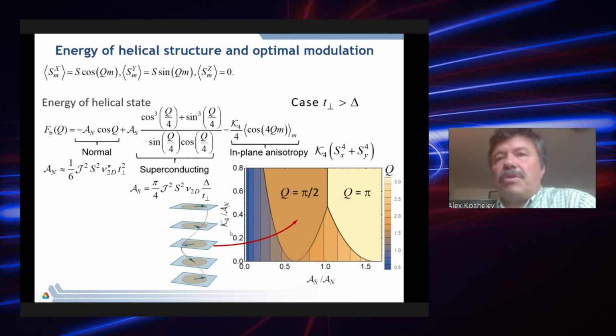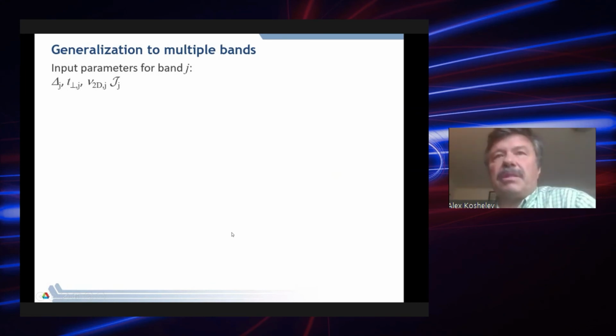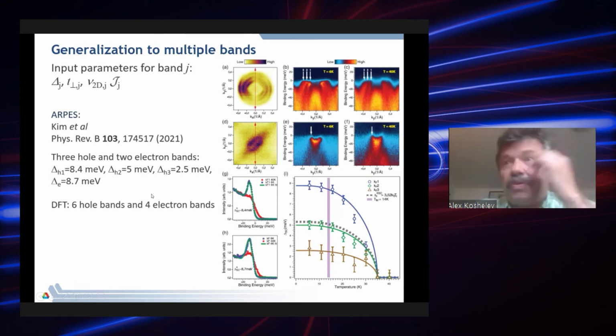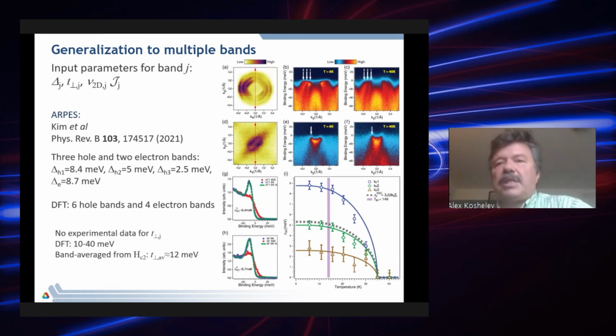This model is of course illustrative and kind of a toy because the material is much more complicated and has multiple bands. To have a realistic model, we need basically the electronic and superconducting properties of these bands. We do have some information about superconducting properties. There is nice ARPES data published, which gives gap values of these bands. What's not available is experimental data for hopping integrals, which is the next important parameter in the model. DFT calculations give values from 10 to 40 millielectron volts, which is slightly bigger than the gaps, and we can also get a band average value, which is 12 millielectron volts, in a good range for this theory.